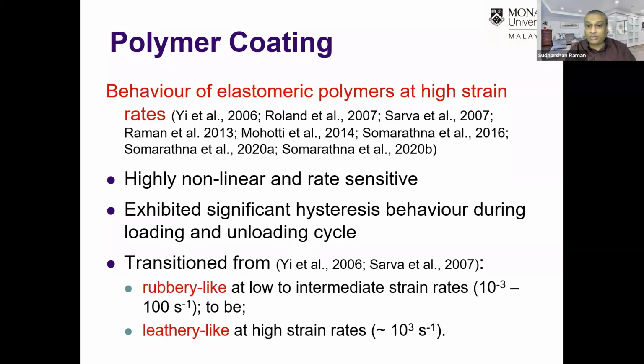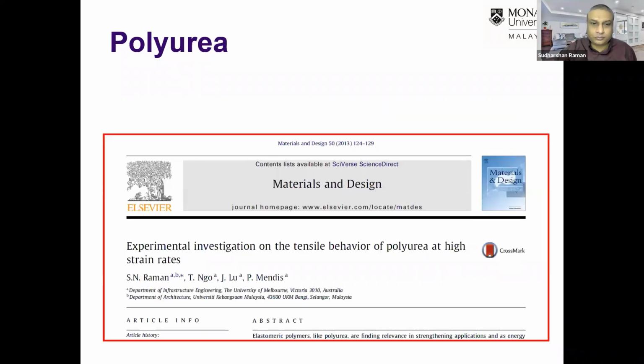What has been found in most of this work is that some common properties of this material are that they are highly nonlinear and rate sensitive. They exhibit significant hysteresis behavior during loading and unloading cycles. At the same time, it was also observed that they transition from a rubbery-like behavior at low and intermediate strain rates to leathery-like behavior at higher strain rates, which means that their E value or Young's modulus becomes higher when they are subjected to a higher strain rate. The material actually stiffens at higher strain rates. This is one of the major observations of this material when subjected to high strain rate loading.